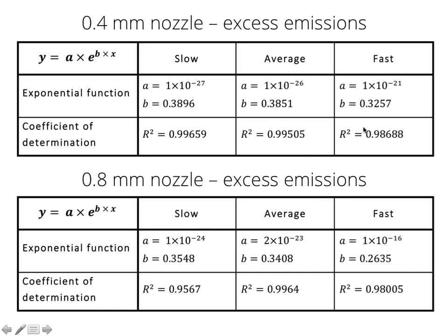Again, the logarithmic slope is quite interesting: 0.38, 0.38, 0.32, 0.35. So the slope is quite similar. Again, fast is an outlier, and A tries to go towards 0.